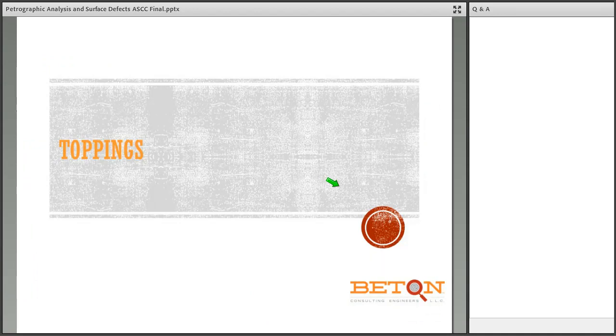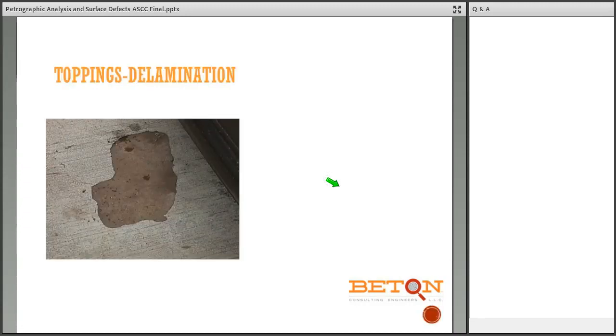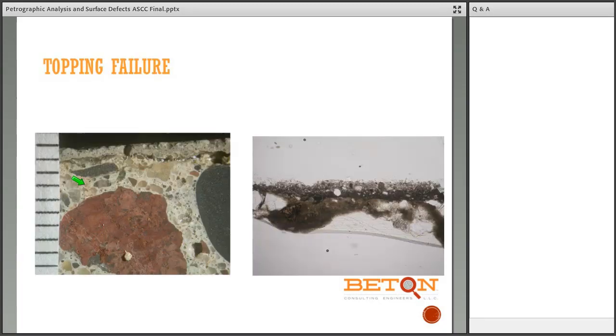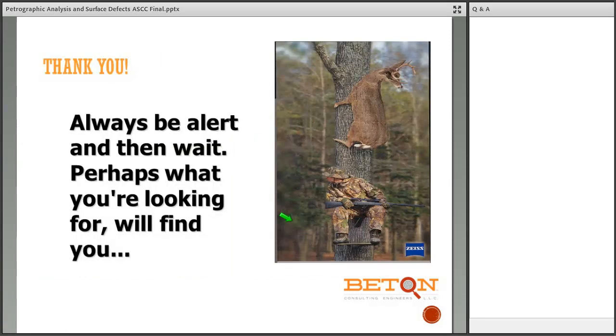Toppings can fail as well. Yep, and basically, you can see on the left here, that's what the topping failure looked like, and when you look at it in polished cross-section and also in thin section, you can see this paste, this is concrete paste from the original top surface, and this is the topping. Detachment occurred within that top surface of the original concrete, and this was all carbonated, and so basically they likely did not remove the unsound concrete before they applied the topping. Very useful in diagnosing problems.